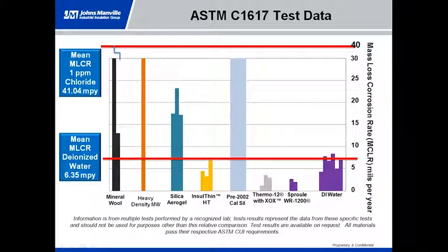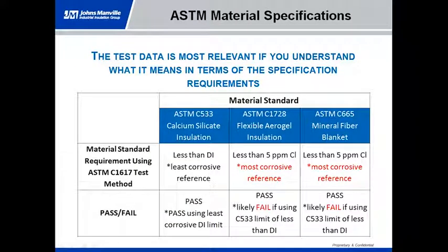reference point, the Thermo-12 with XOX and the Sproule perform much better than that standard. And the InsulThin HT is consistently below it, but at times flirts with that threshold. But the Thermo 12 and the Sproule consistently are better than that. Now, if you look at the mineral wool products and the silica aerogel, they're always consistently below the 1 part per million chloride. So even though they're below a given threshold, you can't say that their performance is equivalent.